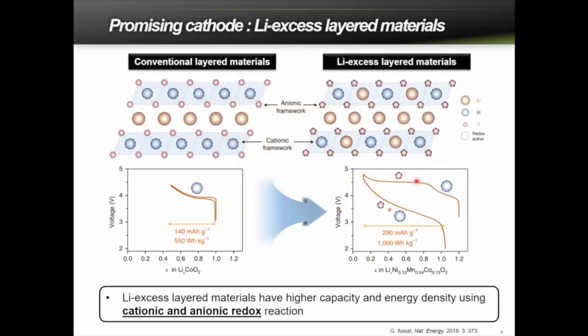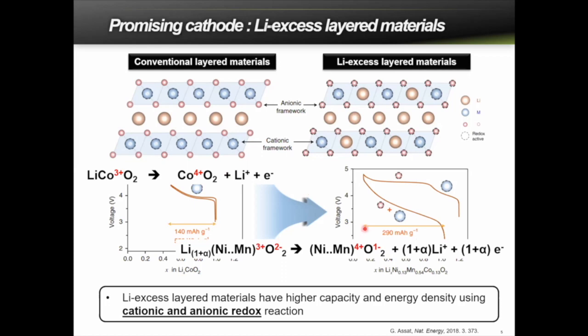One of the interesting findings in recent years was that not only the transition metal, but also the oxygen in these materials can participate in the overall redox reaction under certain circumstances, offering additional room for capacity. In the conventional cathode, the capacity is provided by the redox of the transition metal, and the typical capacity is around 140 to about 200 milliampere-hours per gram at best. But when the anion redox is additionally allowed, we have more sites for electron storage, simply speaking. Therefore, the capacity can be much more enhanced. So in a very simple picture, it is a transition from redox reactions solely occurring at the transition metal to this cumulative redox reaction, from both the transition metal and the oxygen, so that we can store more lithium and more electrons.